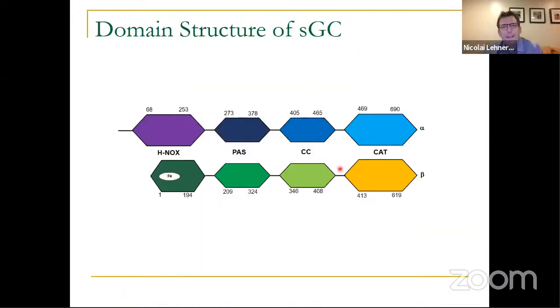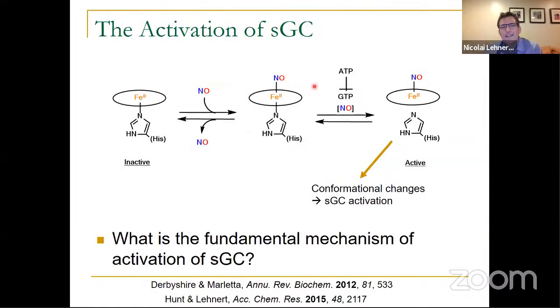If you go back to, yeah, this may be a good one. If you replace NO with CO, carbon monoxide will bind to the heme, or isocyanide will bind to the heme. But in both cases, the 6-coordinate complex is stable. I don't know if people have bound isocyanide, but people have bound CO to soluble guanylate cyclase. There's no activation because it stops here. With CO, you get a stable 6-coordinate complex, it stops. It does not break the iron-histidine bond, and it does not activate sGC. So you just bind CO and nothing else happens. Isocyanide would be the same, but I don't know if people have actually tried it on the enzyme. Both of those ligands do not have the strong sigma trans effect that NO has, and so they cannot activate soluble guanylate cyclase.